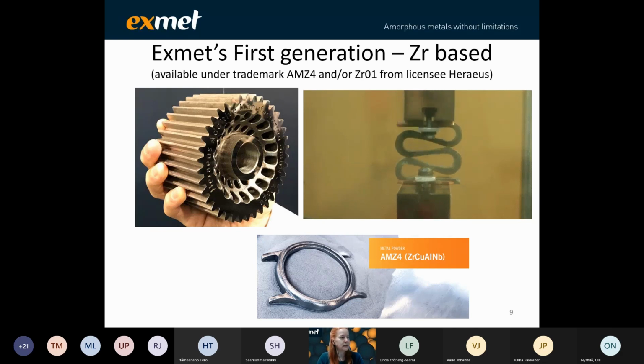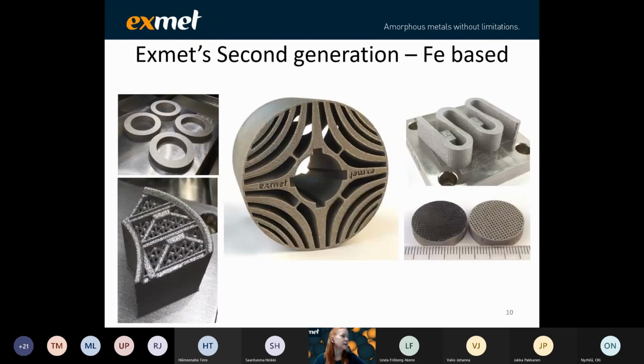And that's a well-known family of alloys in the amorphous world. I show it today to say that this is where we have proven the first feasibility results, even though it's not very interesting for the webinar today. These are our more mature materials, and they are now commercially available through Heraeus, our licensee. Our second generation materials are iron-based, which is a more demanding material for us to process, and even more difficult to process using the conventional amorphous manufacturing methods.